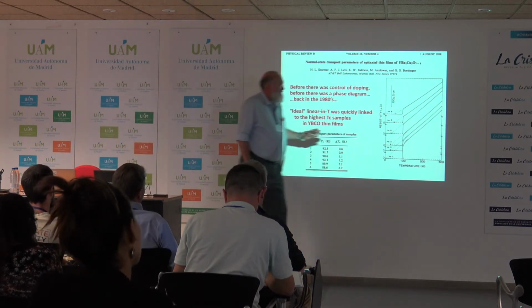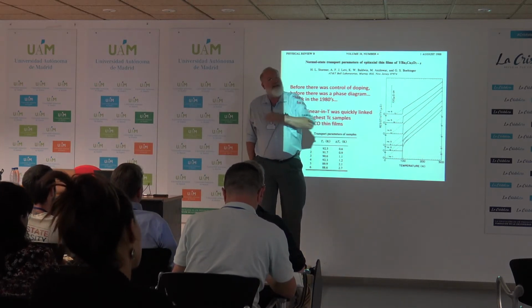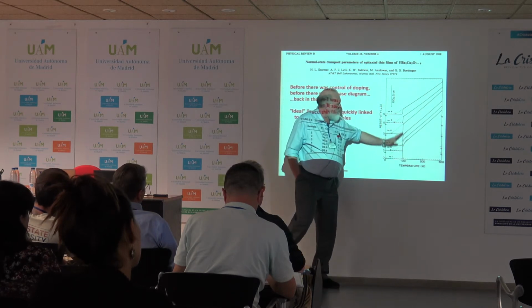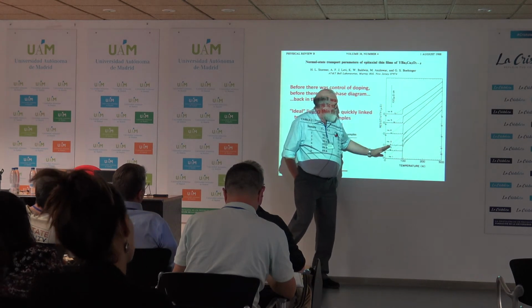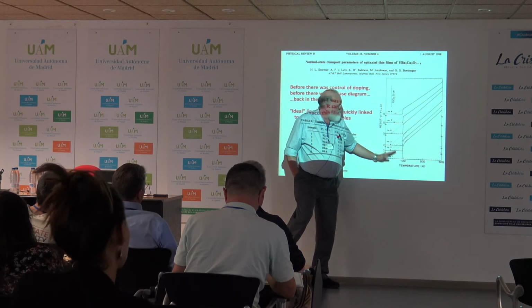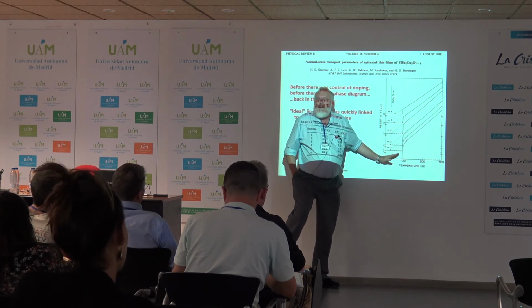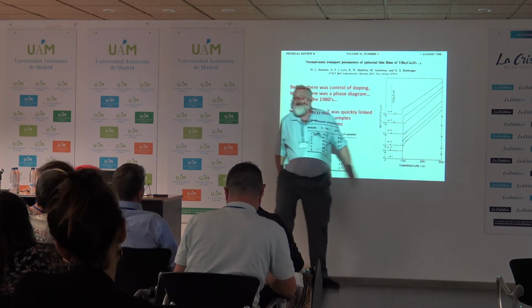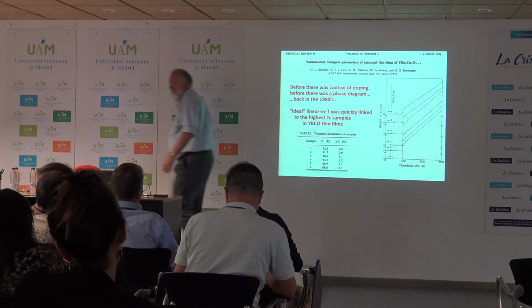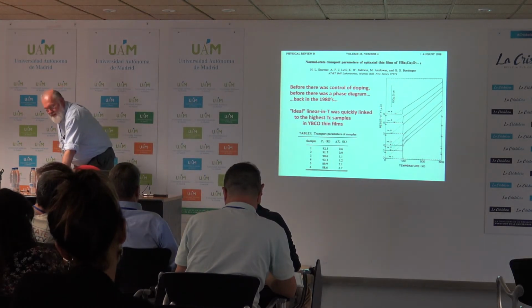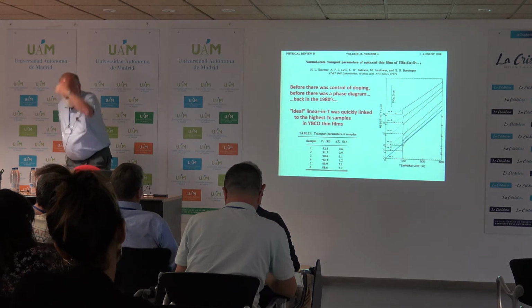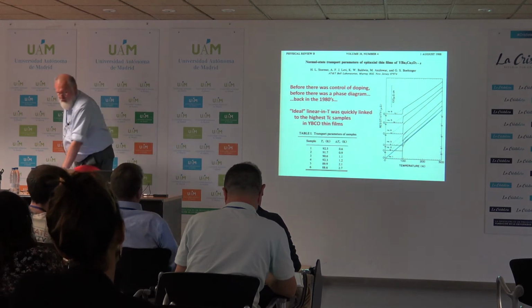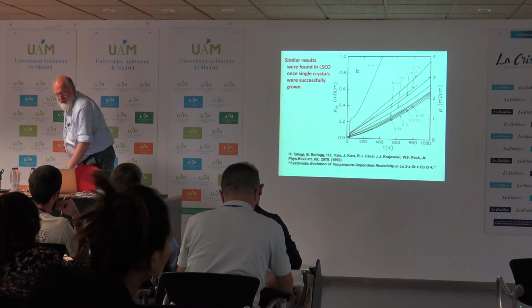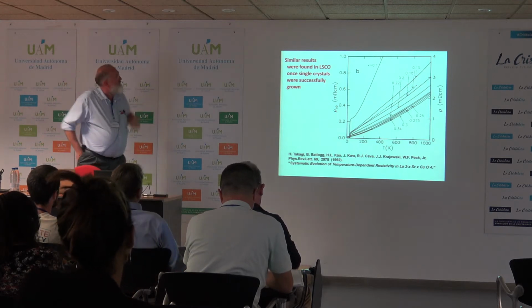But as you saw in the previous talk, and you'll see in this talk, there are many materials for which the slope is linear, but the intercept is finite. And we still have this prejudice, perhaps, that the ideal behavior is when the intercept is 0. And I'll point out that we've now achieved that. Ivan Bozovic's group, in particular, has achieved that in LSCO thin films formed by MBE. So similar results were found in LSCO.